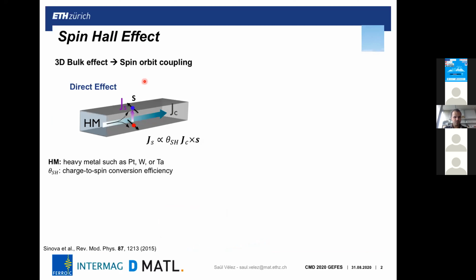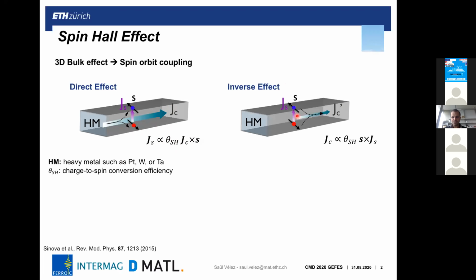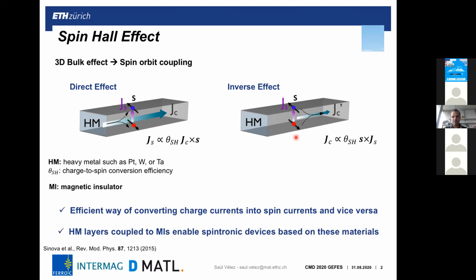To start with, how do we generate the spin currents in all these devices? We use the spin Hall effect, which exploits the spin-orbit coupling of materials to generate spin currents. In a material such as platinum, when we run a current through it, you generate a transverse spin current. The efficiency of this effect is given by the spin Hall angle, and by the reciprocal process, from a spin current you generate a charge current. This allows an efficient way of generating spin currents and also detecting them in devices. Of particular interest for us is that we want to use these spin currents to manipulate, or make possible, spintronic devices made of magnetic insulators, in which charge currents cannot flow, but spin currents can be injected through the interface with a magnetic insulator.